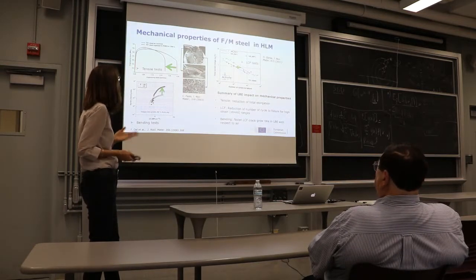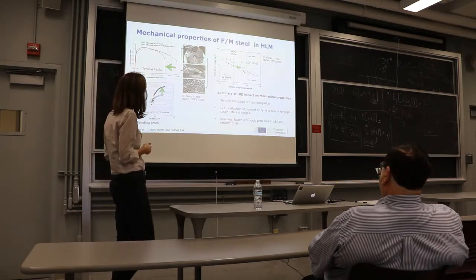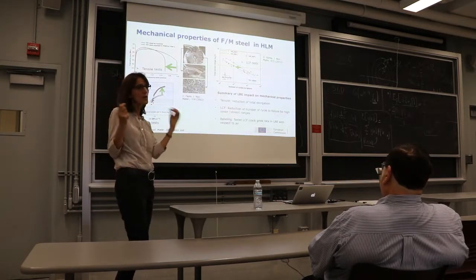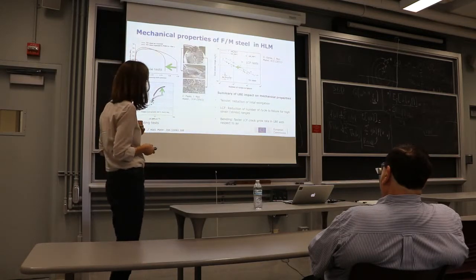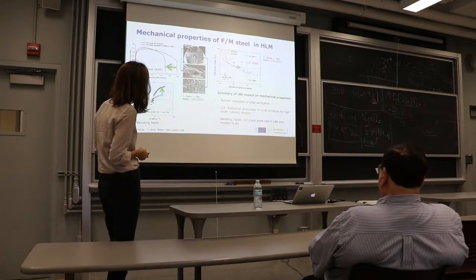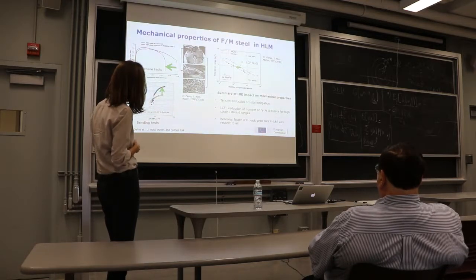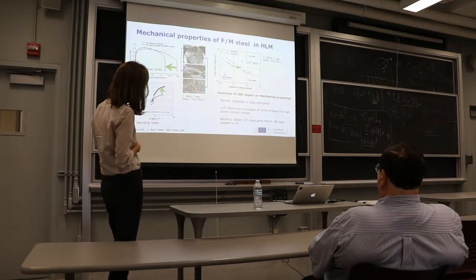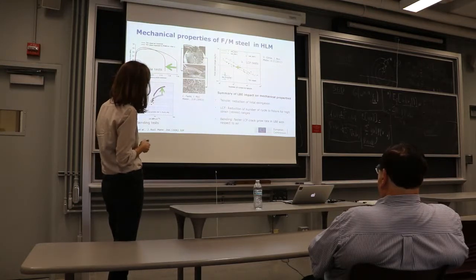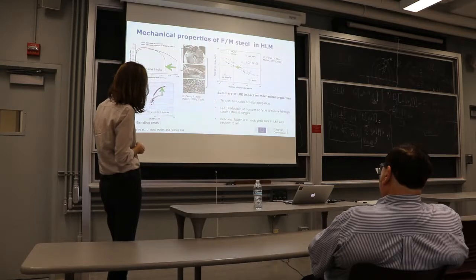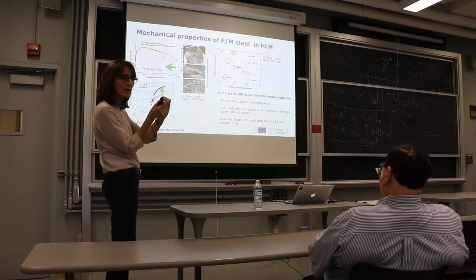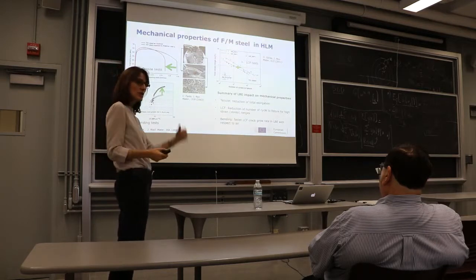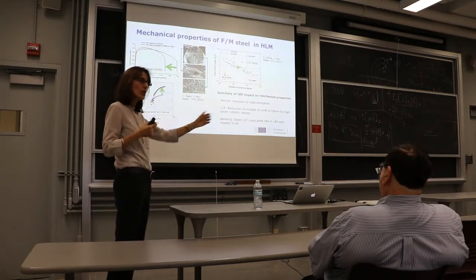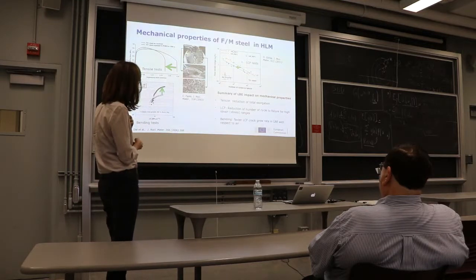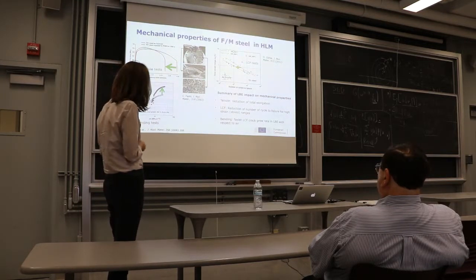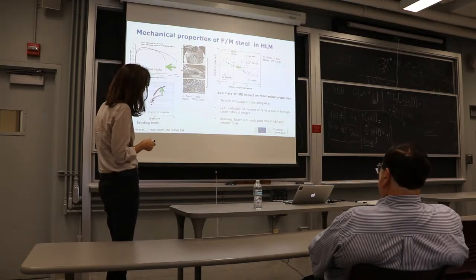And as I told you before, what happens when the liquid metal penetrates inside the steel, so the oxide scale maybe is not there or it's broken, then there is a complete degradation of the mechanical properties. You see it here, there's some tensile test results. Here's again the uniform elongation that goes down. This is the ferritic martensitic steel. Or here you see that if you have a crack on the material and you put the crack under tension in the liquid metal, the crack starts to grow, and it grows much faster if it is in the liquid metal. So the liquid metal helps it much more with respect to air.